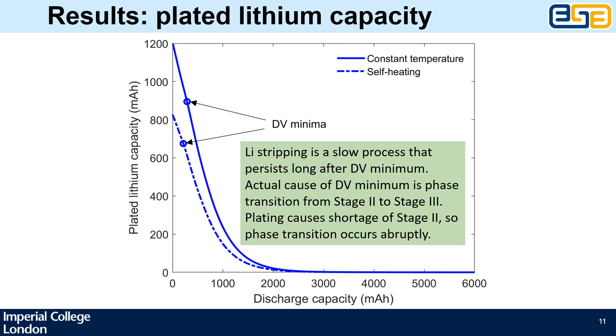Just like Yang et al and Lun et al previously, I've also plotted plated lithium capacity versus discharge capacity, but unlike them we found that the points where the dV minima occurred were nowhere near the end of stripping. Looking more into it, the actual cause of the minimum is the phase transition from stage 2 to stage 3 during discharge. What's happening is the plating of lithium causes a shortage of stage 2 in the graphite particles, so the phase transition occurs abruptly, which leads to that sharp feature that you see.